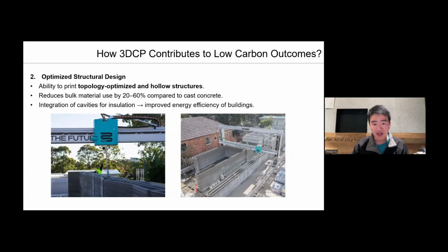Another way 3D concrete printing drives low carbon outcomes is through optimized structural design. With this technology, we can print topology optimized and hollow structures that traditional methods find very hard to achieve. This means we are able to reduce bulk material use by 20 to 60% compared to standard cast concrete. On top of that, we can integrate cavities for insulation directly into the walls, which improves the overall energy efficiency of the building and reduces its operational carbon footprint over time. So it is not just about building differently, it's about designing smarter, lighter, and more sustainable structures.